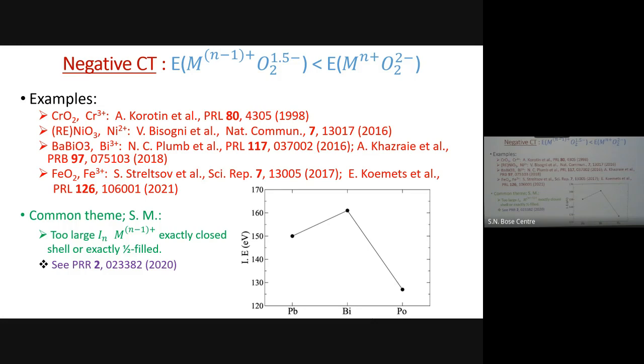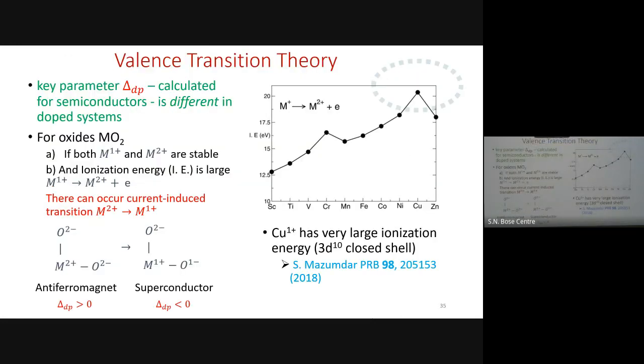I don't understand one system, but there are about 8 or 10 negative charge transfer gap systems until now. All of them satisfy this condition, that the lower charge, chromium 3 plus, once you put it in the crystal structure, is exactly half filled. So if you do that, you will see these peaks at closed shell and half filled. Every time you have exactly half filled, putting in the crystal structure, but exactly closed shell doesn't have anything to do with crystal structure.